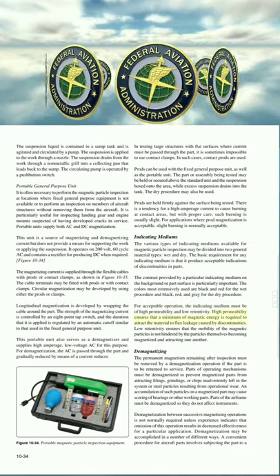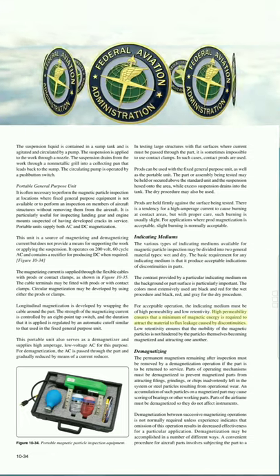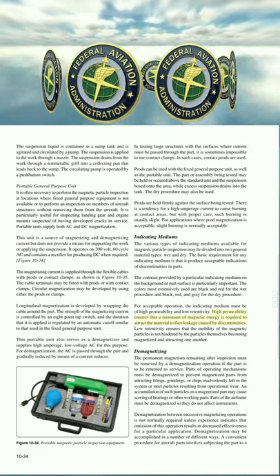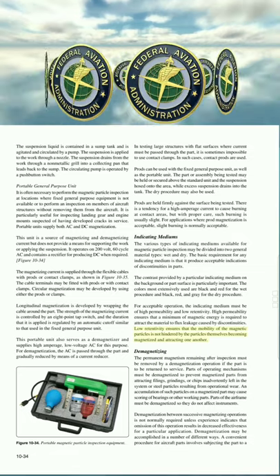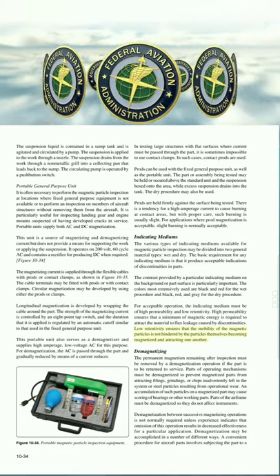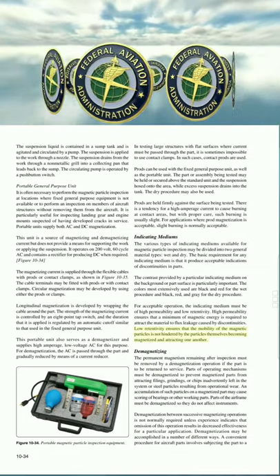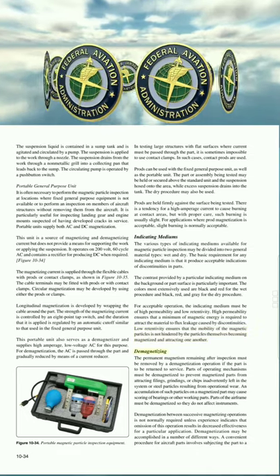For acceptable operation, the indicating medium must be of high permeability and low retentivity. High permeability ensures that a minimum of magnetic energy is required to attract the material to flux leakage caused by discontinuities. Low retentivity ensures that the mobility of the magnetic particles is not hindered by the particles themselves becoming magnetized and attracting one another. Demagnetizing.